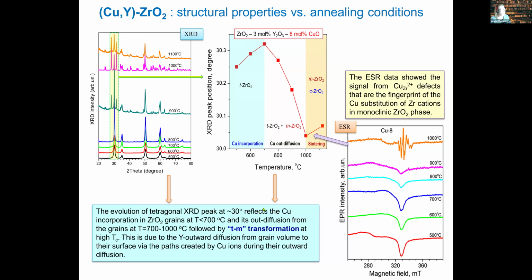If we combine the results of X-ray diffraction and electron spin resonance, we can say that we have the possibility to monitor transformation of crystalline structure and to follow the tetragonal to monoclinic transformation. And we see the formation of a specific fingerprint that tells us that monoclinic phase exactly exists.